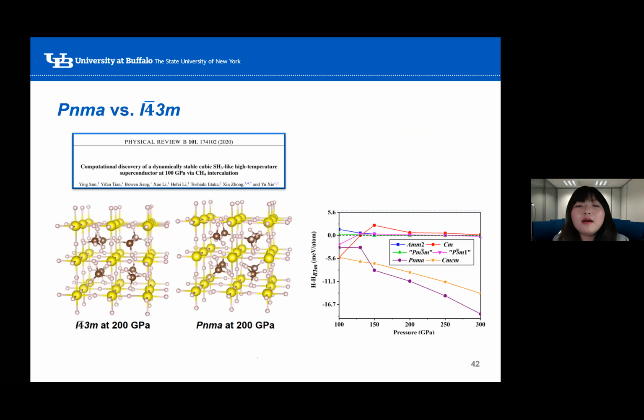So when we have more formula units in the primitive cell, we found that varying the orientation of the methane molecules might further stabilize the structure at higher pressures. That's how we found the Pnma structure. Soon after we published this work, another study identified an I-43m structure that's very similar to the Pnma phase we found. And the enthalpy difference between these two structures is very small, actually within the convergence criteria of the calculation.